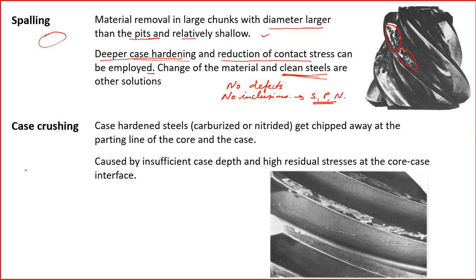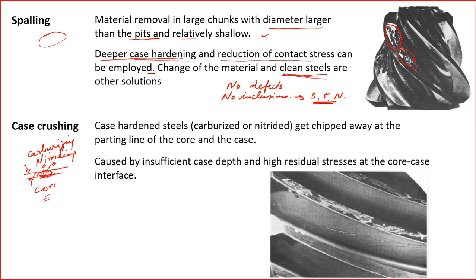Case crushing occurs in case hardened gears which have a hard outer case and a softer core. Carburizing or nitriding produces a very hard case while the core remains soft. Case crushing happens when the case gets chipped away — it is dislodged at the parting line between the core and the case, where residual stress or stress concentration can initiate cracks. Once the case material is dislodged, it becomes a third body causing abrasive wear and leading to complete failure.